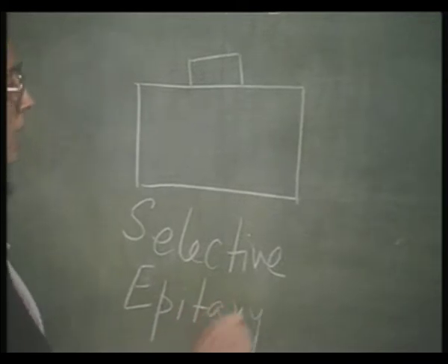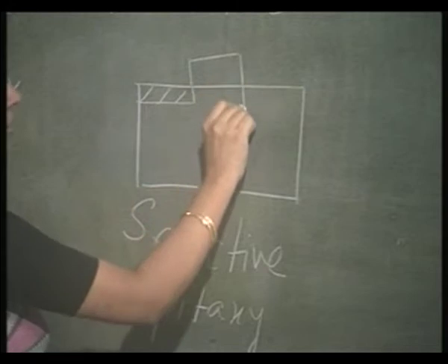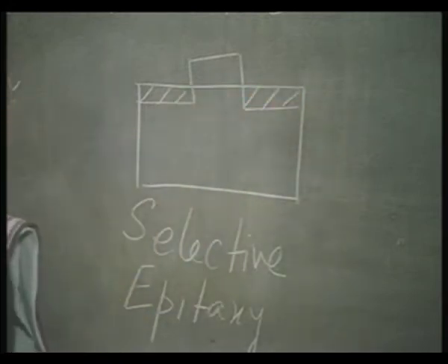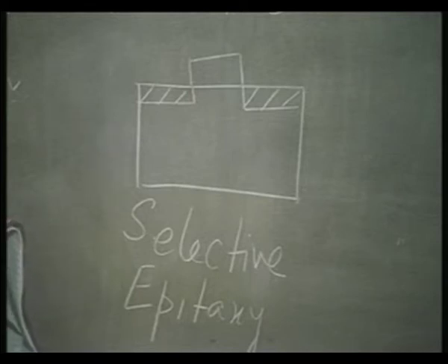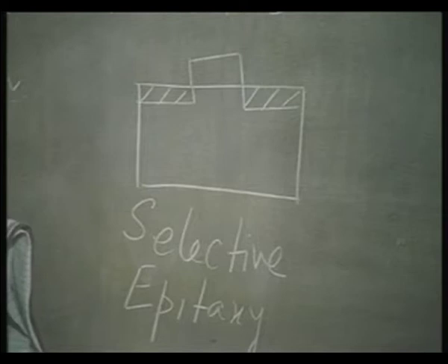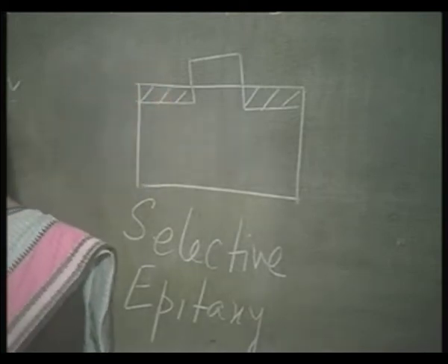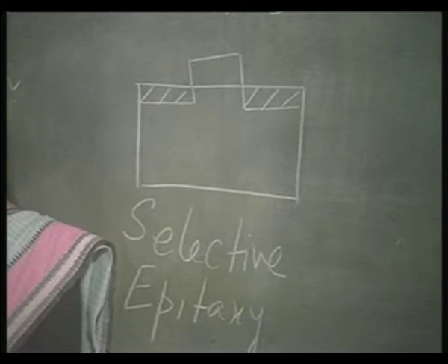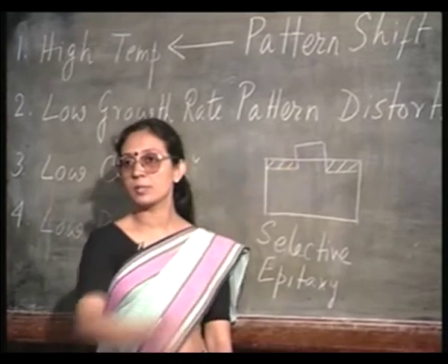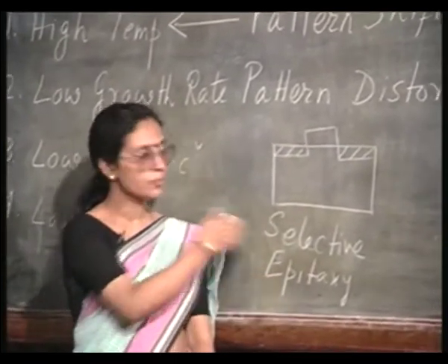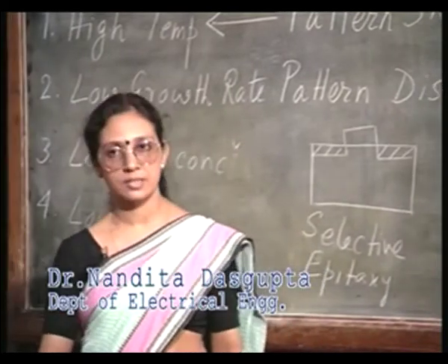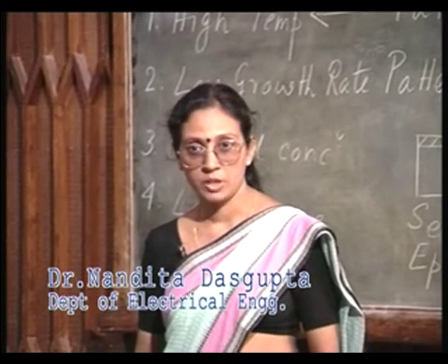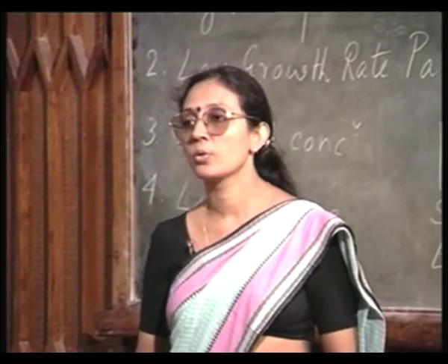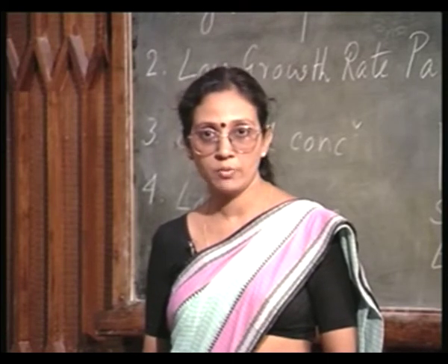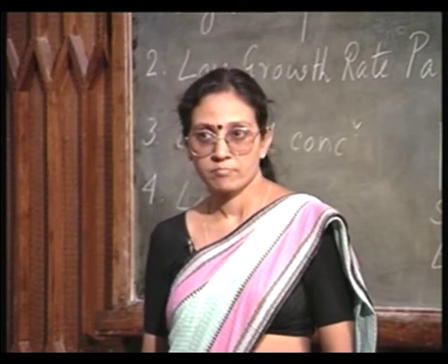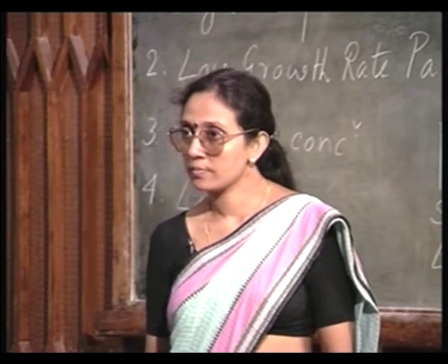This is usually done by covering the regions where you do not want epitaxy to take place with silicon dioxide or sometimes polycrystalline silicon, and then carrying out the epitaxial process, controlling the temperature and the growth rate, so that the epitaxial growth is only taking place on the exposed silicon. See, it is quite simple to understand. Suppose you have the surface covered with oxide, only there are some windows in which the underlying silicon is present. Remember, the chlorosilane reaction is actually surface catalyzed. So, only where it is coming in contact with the silicon surface, epitaxial growth will take place.